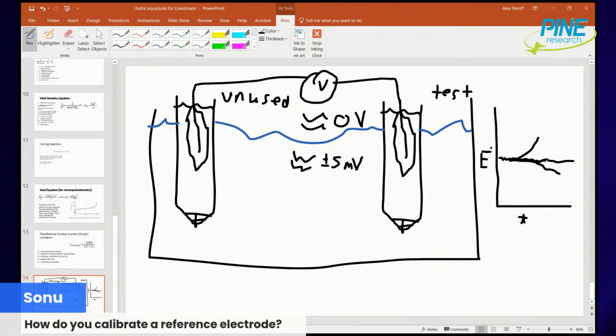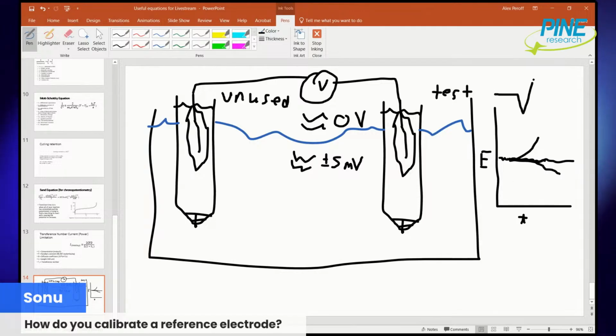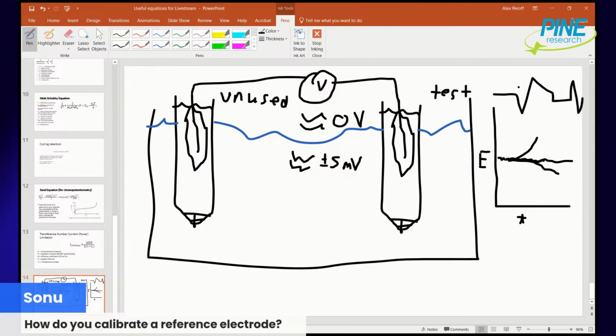And make sure you look at the y-axis, because sometimes potentiostats will zoom in if there are no big changes. So you may see something that looks crazy, but it's actually fractions of microvolts, so it's not a crazy result. You want to make sure the reference electrode is stable. This is a great way of making sure that your reference electrode, especially your test reference electrode in your system, is working. Now, in terms of calibrating, how do you know whether your unused or your test reference electrodes are even good in the first place?